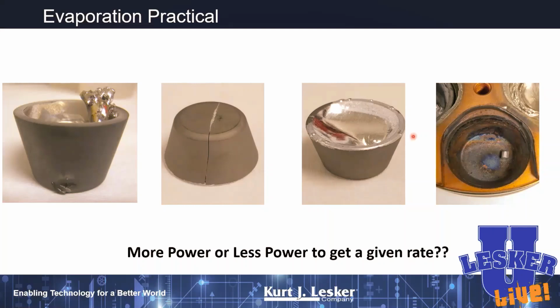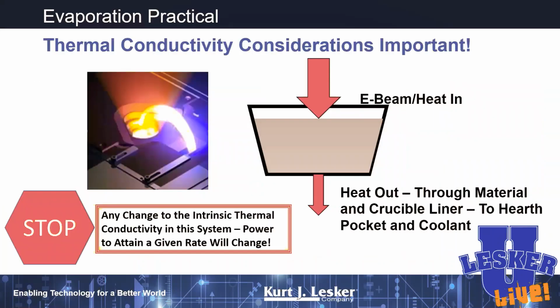Don't overfill your crucibles. If you overfill them, let's say more than two-thirds full, as that material gets molten, it will crawl out of the crucible and attack the gun. That's considered bad. Make sure you don't have any junk lying down in the pocket of your gun. So here's a gun where somebody left a pellet down below, and then when they put their crucible in, obviously the crucible wouldn't sit flat, and they got some very, very strange behavior. So just be mindful of that. Know also that the heat's coming in from your E-beam, and you're hoping that it goes out the crucible for some materials. So just be mindful about the heat flows in your E-beam system.